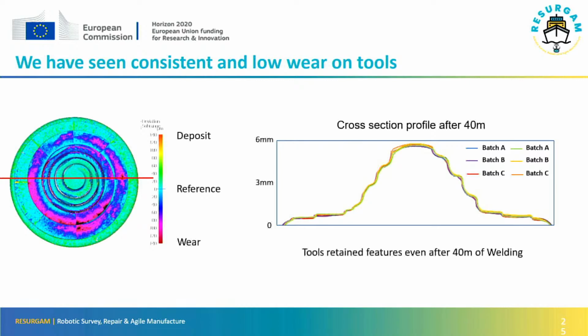So we took the tools, we laser scanned them to build up a 3D image of the tools. We then did several welds with them, scanned them again, made more welds, scanned them, and measured the wear on those tools. And what we were finding was that even after 40 meters of welding, the wear was measured in microns. So that was good enough. You know, we could still make a good weld if the tool had only changed its dimensions by a few tens of microns. The competitor tools had worn out or broken at that stage.